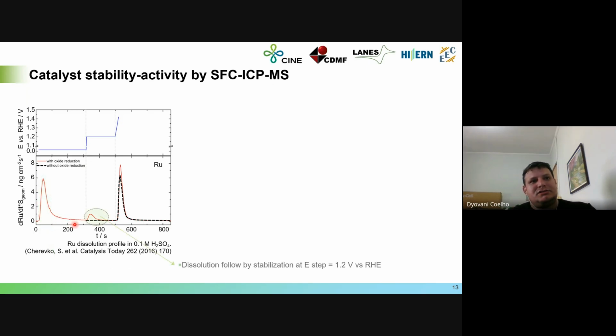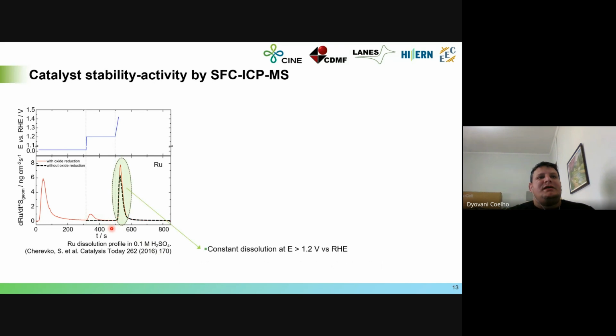And then they apply a step potential of 1.2 volts. And there is, again, another dissolution of ruthenium that stabilizes. And then they perform a potential scan. During the potential scan, in the same potential range where the oxygen evolution reaction occurs, they see a constant dissolution of the ruthenium that stops when the scanning stops. So this means that the catalyst is dissolved over time during operation, during the oxidation.